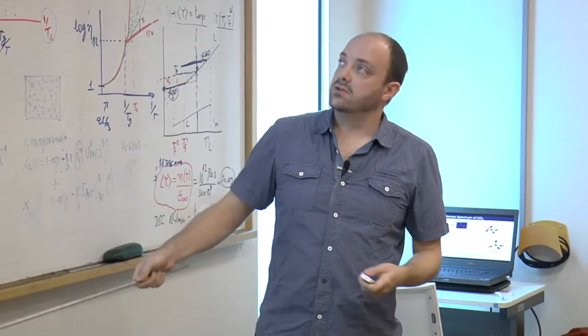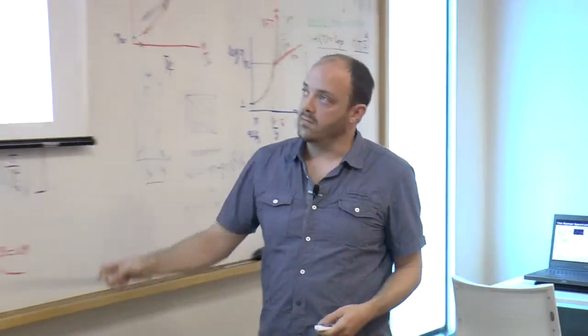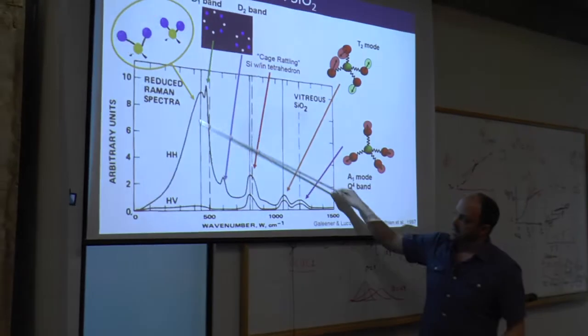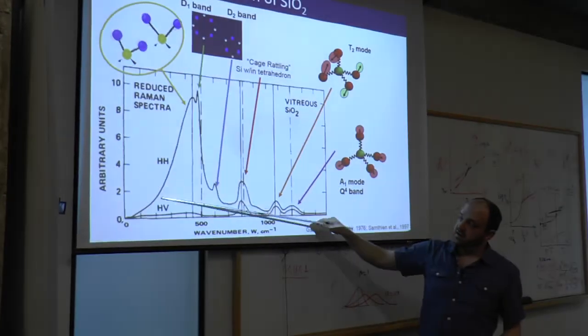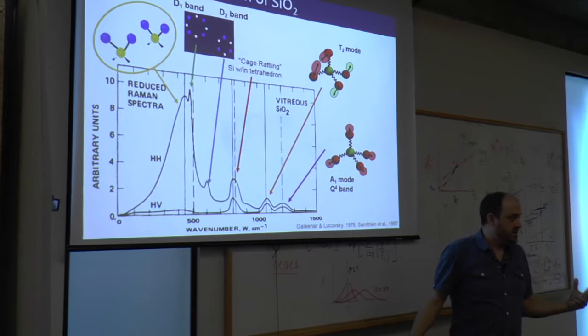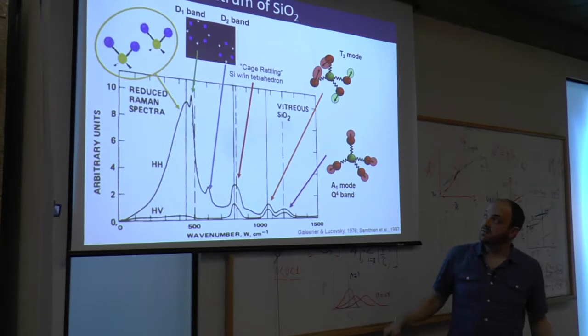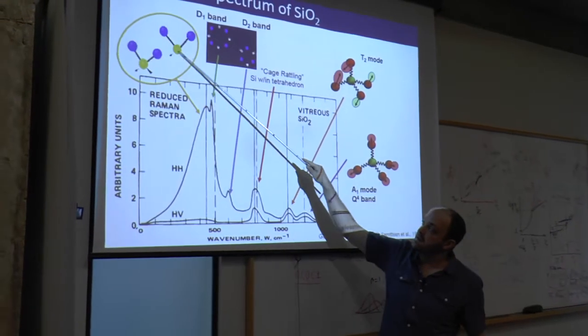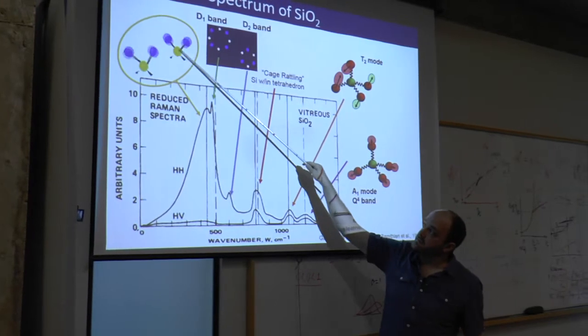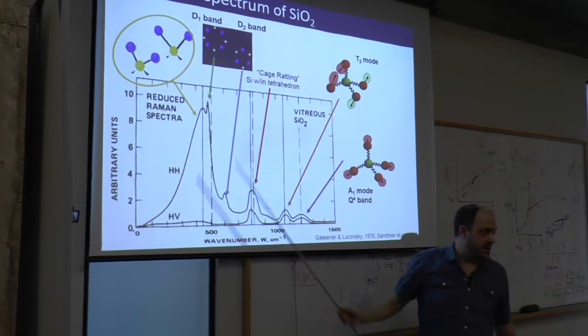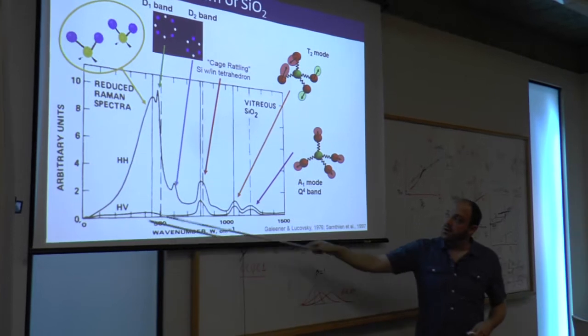So before I take a break, I'll just go through a few more slides, but let's look at the actual spectrum of silica since it is the most studied. This really broad band, it's not 100% clear that it belongs to one specific bridging oxygen vibration, but it probably represents that. It probably is related to a symmetric stretch as well as some rocking motion within the network.